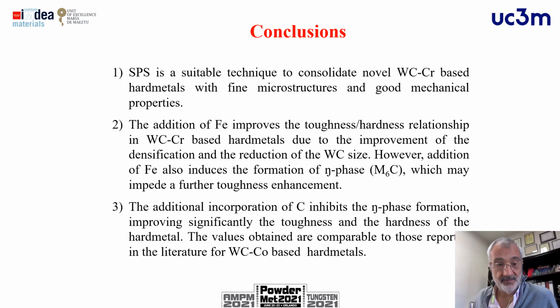So as a conclusion of this work, and trying to be on time, we can say that the spark plasma sintering is a suitable technique to consolidate these novel tungsten carbide chromium-based hard materials with very fine microstructures and good mechanical properties. The addition of iron and carbon improves the toughness hardness relationship in these hard metals, and if we put only iron, it can induce the formation of eta phase, which is brittle and we have to avoid, but the addition of carbon can reduce these amounts of eta phase and can allow us to get a good combination of properties.